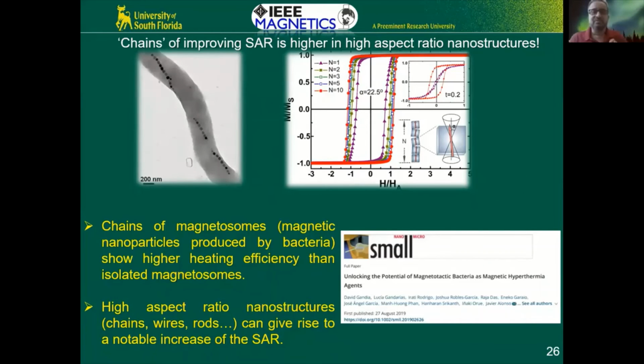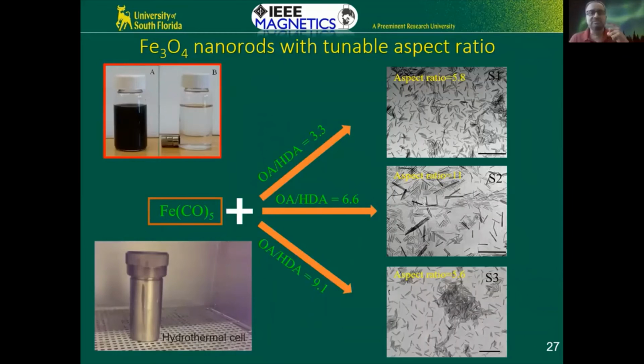And then there's another postdoc in my group, Raja Das, who decided to mimic these short chains in the bacteria. And instead of having chains which are weakly coupled, right, dipolar coupling is not very strong, he wanted to make nanorods. These are robust nanorods of magnetite. I would say some of the best nanorods that you will find out there. And the best way to make them is using a hydrothermal technique. This is like a pressure cooker. It's a pressure cell. So you basically cook these nanoparticles at high pressure. In addition to temperature, time, and surfactants which control the growth of these nanoparticles, you add another variable, which is pressure. When you do that, you can actually control the aspect ratio. You can produce really good nanorods.